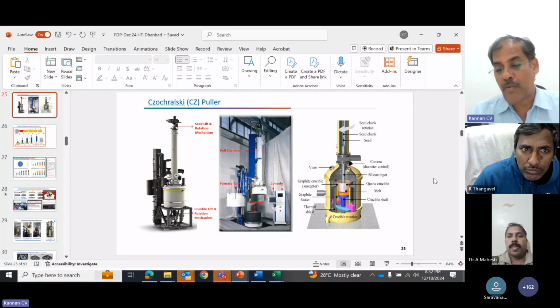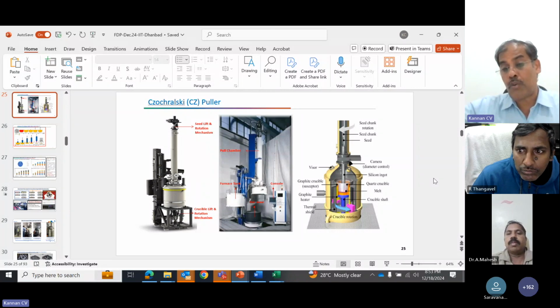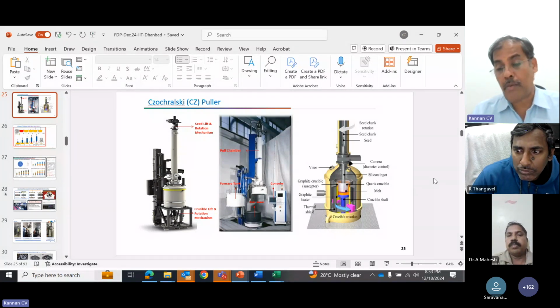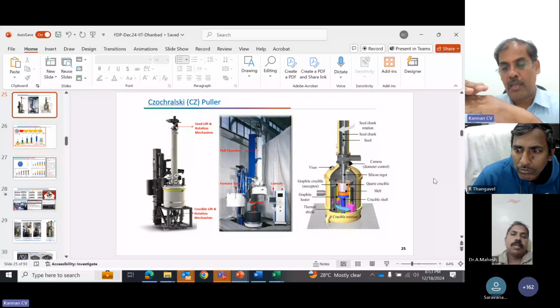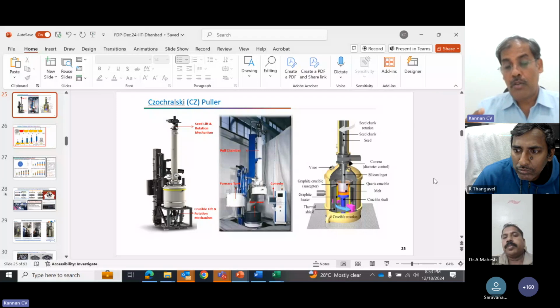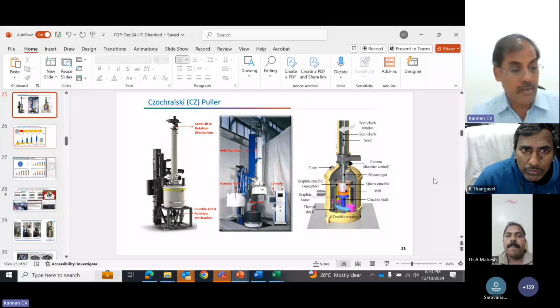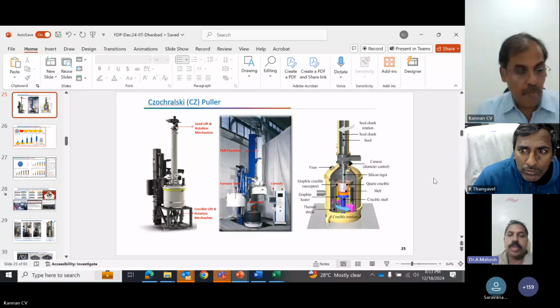The slide I showed is from 2012, but actually multicrystalline silicon efficiency has become 18, 19%, whereas monocrystalline has gone even to 25, 26% with the technology advancements happening only in monocrystalline. Because of the limitation in multicrystalline efficiency, all the new technology is focusing on monocrystalline, where there is potential to increase the conversion efficiency further because there are no grain boundaries. So grain boundaries are basically trap areas. But the commercial efficiency now available in the market is around 20-21% only, sir.